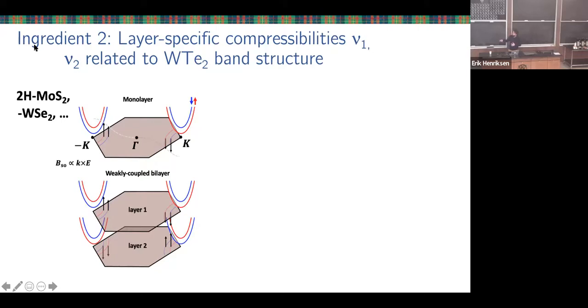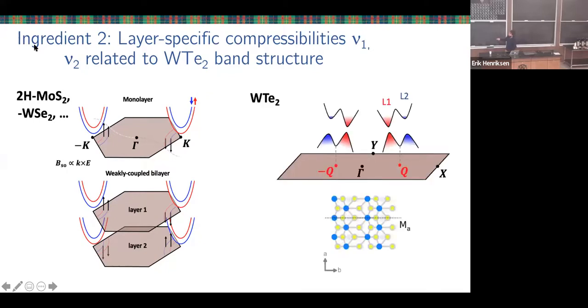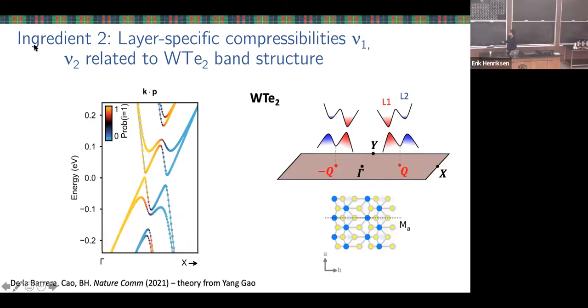So there's an intimate coupling, due to spin orbit coupling, of layers and valleys in this material. In WTe2, there's a similar effect: if I tell you what valley you're in, I can tell you also what layer you're in. It's really the spin orbit coupling in the band structure that allows you to have these layer polarized wave functions in the material. That's interesting because that's very different from the reason the same thing happens in bilayer graphene.